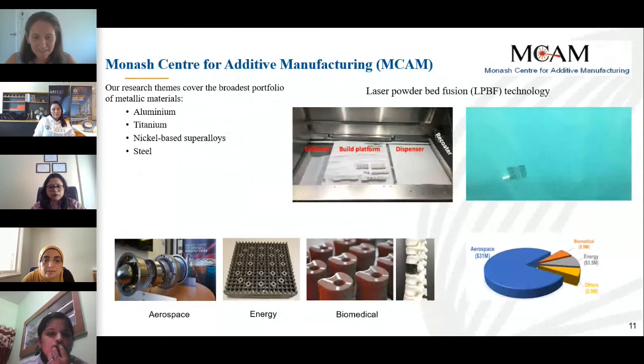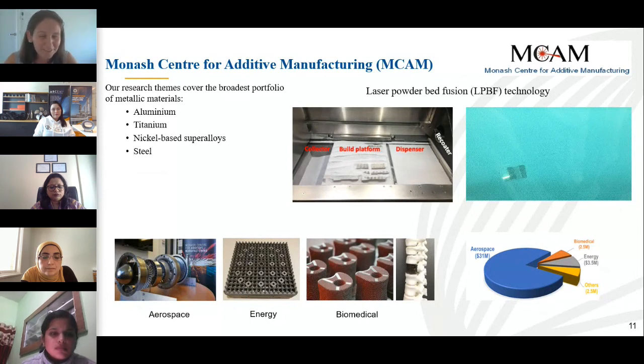Sounds like you can mitigate it quite well, though, by changing the chemistry of that alloy and swapping out some of those lower melting temperature elements and putting in higher melting point ones. In my PhD work, I was working with titanium, but also tantalum. And tantalum is a really refractory metal that does not melt very easily. So we had to use very, very high energy densities to try and get the tantalum to melt without the titanium evaporating, because the melting temperature for tantalum is actually just a few degrees higher than the evaporation temperature for titanium. So getting them molten at the same time is quite difficult. But as Dina mentioned, there's a little bit you can do with processing parameters as well as alloy control.